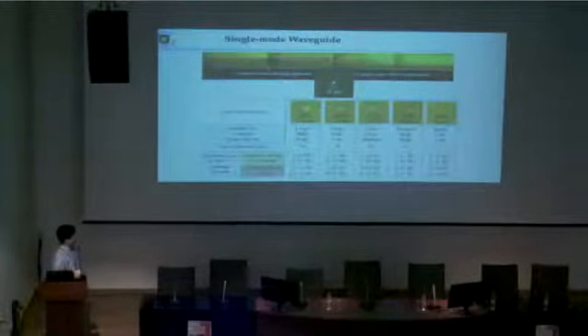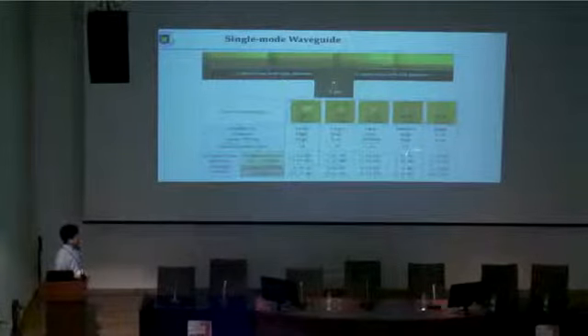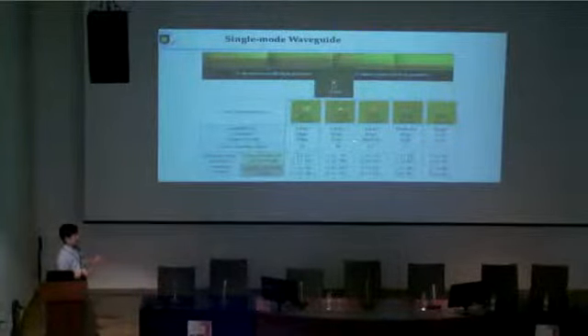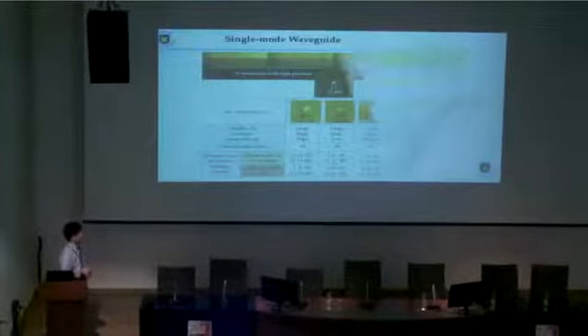And we evaluated the insertion loss of these waveguides. The core diameter of 12 micron showed the best insertion loss when these waveguides are inserted in 2 single mode fibers. So we still need to optimize the dispensing conditions for obtaining a good single mode waveguide. And this is the data presented at ECTC last week.